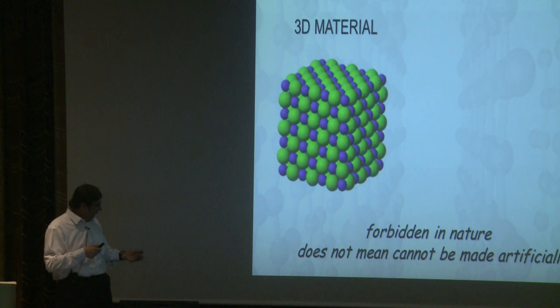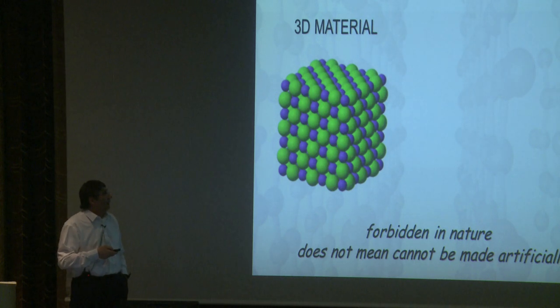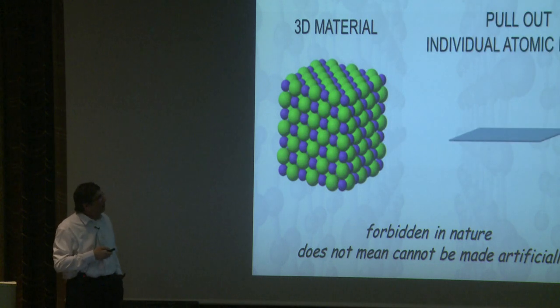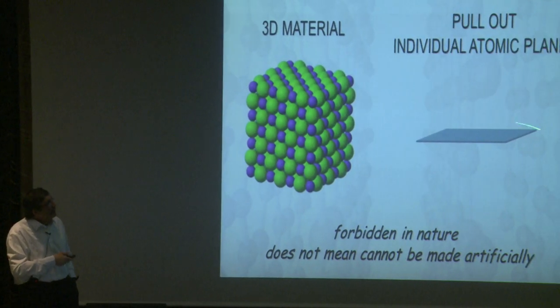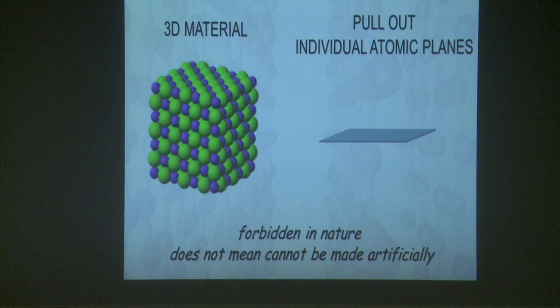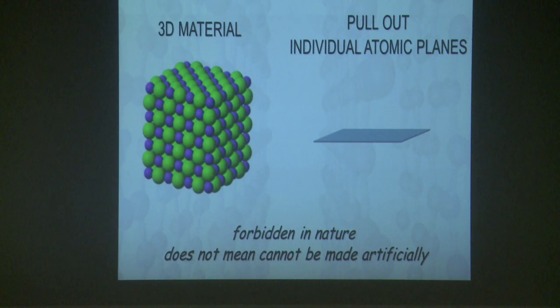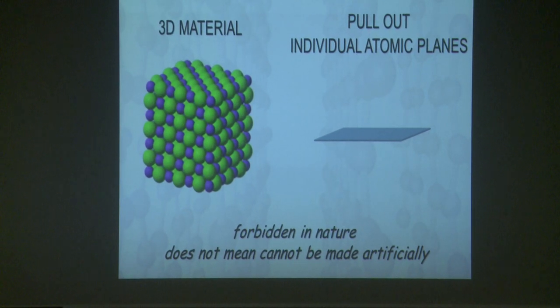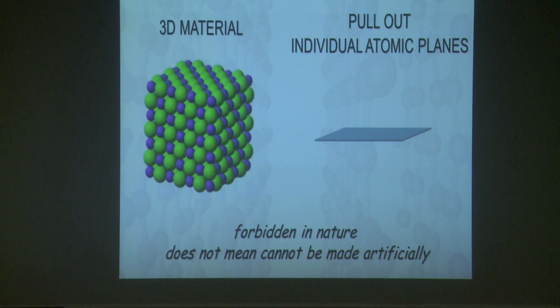No problems with that. So, because it exists in our conditions, you can think about taking very small tweezers, and with their help you pull an atomic plane out of those. That's allowed by the laws of physics, because the high temperature needed for growing materials is no longer present. We live at a relatively low temperature, our room temperature conditions. And materials like graphite have to be grown at temperatures of 3,000 centigrade. So room temperature is not really a problem for them.